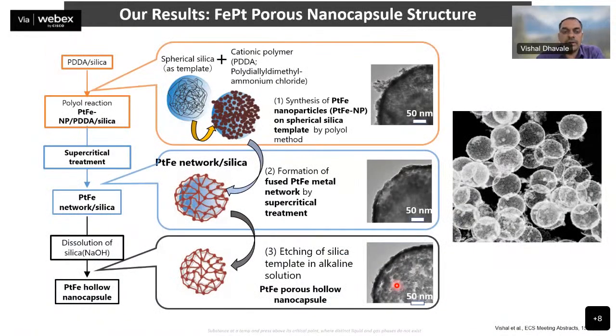So this was another case study where we studied the iron platinum porous nanocapsule structures. You can see the very distinctive porous network of this FePt nanocapsule structure, which is synthesized with a modified polyol process. First we use a template like silica. The silica surface has been modified with PDDA to create some cationic network on the silica surface, and then these FePt nanoparticles can be supported over here, and sequentially you can reduce. Once it gets reduced, you can have such kind of particle decoration on the silica particles, but these are not connected. So to interlink these particles from this step to this step, we do a certain modification, a certain protocol that is called supercritical treatment.